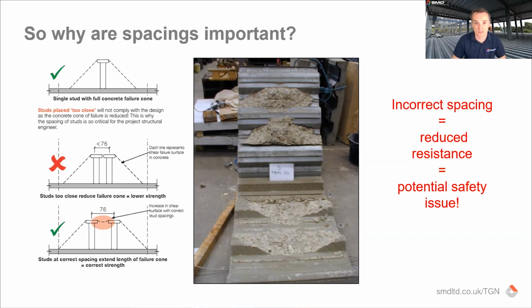To understand why spacings are so important, I'm going to take you back to what we said about how studs fail. If we appreciate here that a single stud, we saw, looked like that. The cone of failure is not quite 45 degrees because you get an extension created by the trough, but the principle is that. So 76 is the minimum between a pair within the standard. And obviously, if we put studs closer than 76 together, then you reduce the concrete shear surface that the stud would fail in. By pushing them 76 apart, you're increasing the concrete shear surface by this middle area. And obviously, the further you increase those, the better the stud resistance will be, until you get to a point where they would actually act isolated.